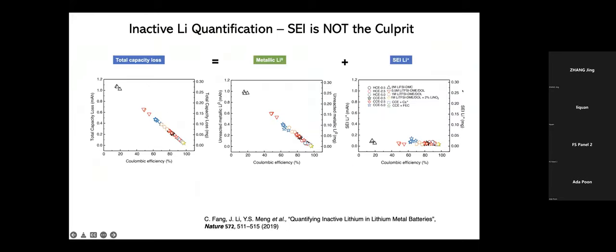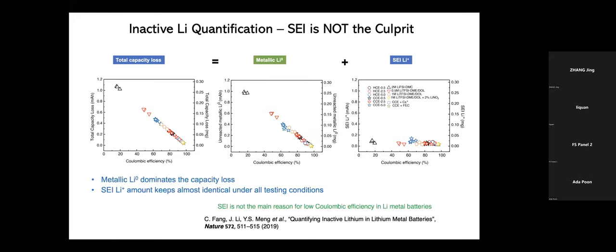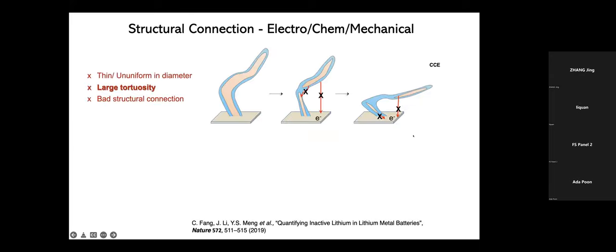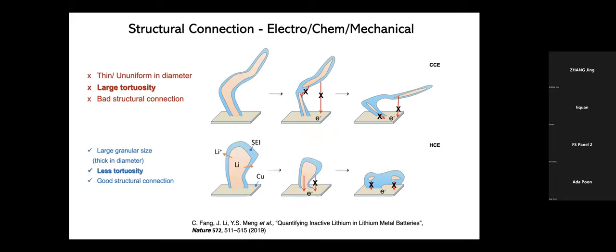And the study really taught us that in the low efficiency lithium metal cells, the total capacity loss is completely correlated with the hydrogen generation, which means the dead metallic lithium trapped inside the SEI. And the SEI, at least in the low efficiency cells, is not the major culprit. It doesn't mean SEI is not important. We just mean on the low Coulombic efficiency side, SEI is not the main reason.